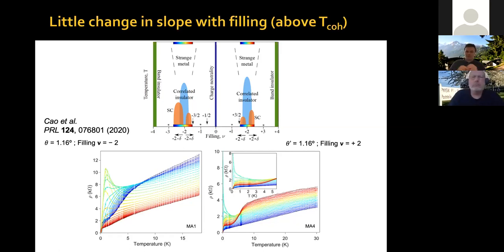You mean at the charge neutrality point? No, not at charge neutrality, the band insulator at 4 electrons per moiré unit cell, or at 4 holes per moiré unit cell. Okay? Because we see these big insulator states, high resistance states, and we know it corresponds to that band insulator. We know that that density, that gate voltage, corresponds to 4 electrons per moiré unit cell. Because we know what the density is, we know what the area of the moiré unit cell is, and if you know the area of the moiré unit cell, you know what the twist angle is, because the area of the moiré unit cell depends on the twist angle. Okay, so that's the simplest way of determining the twist angle.